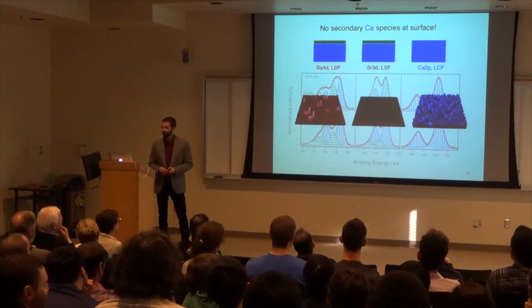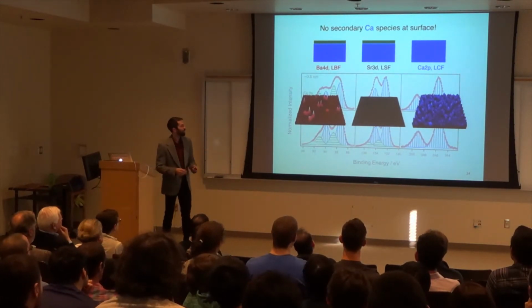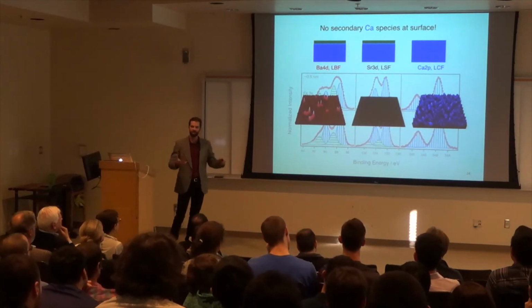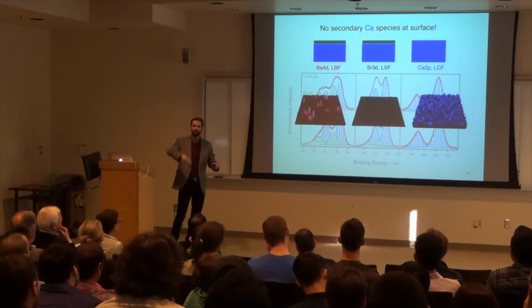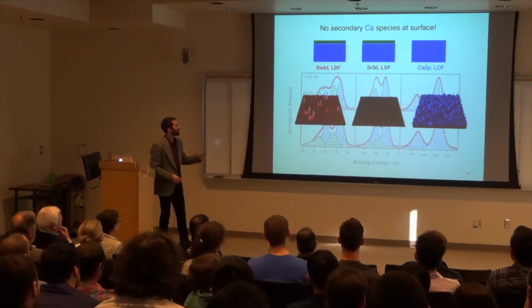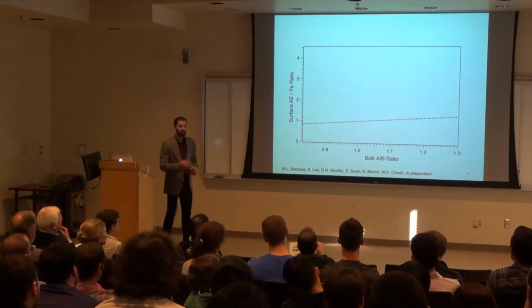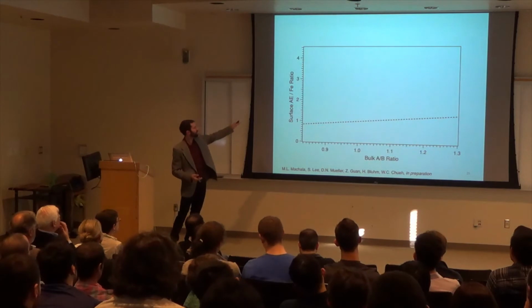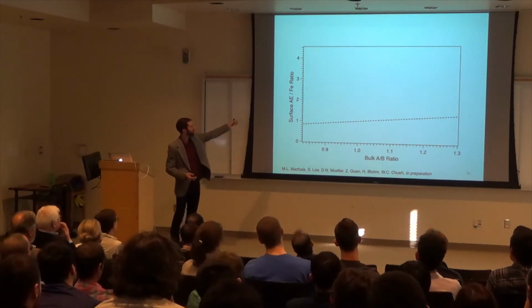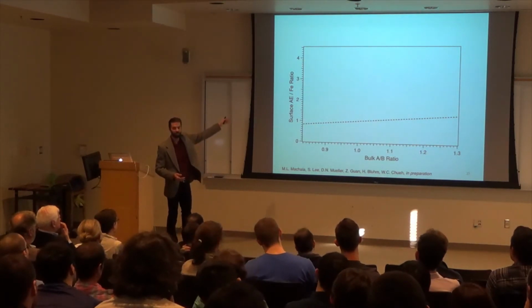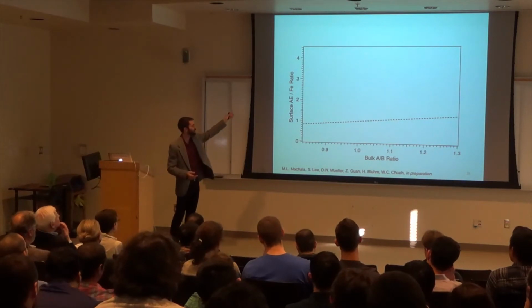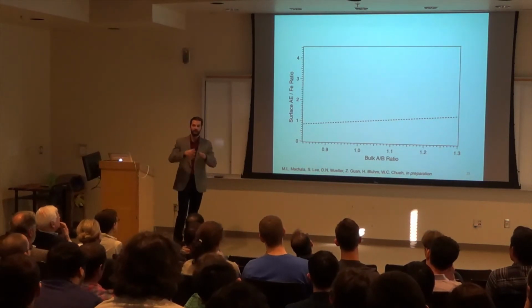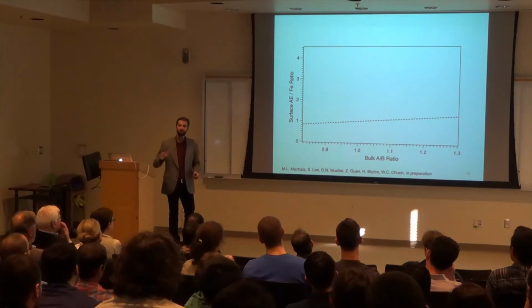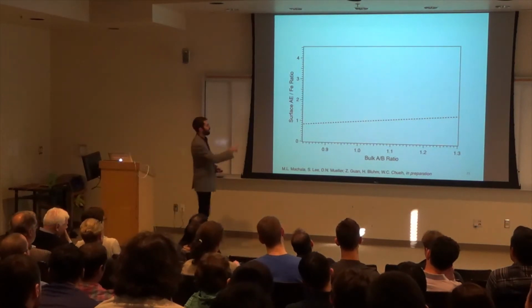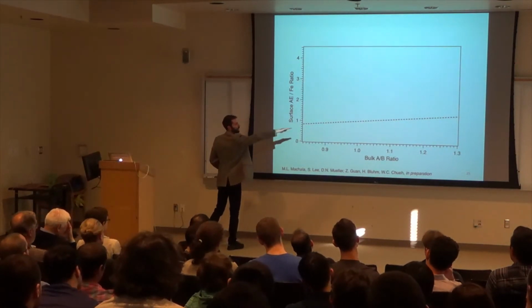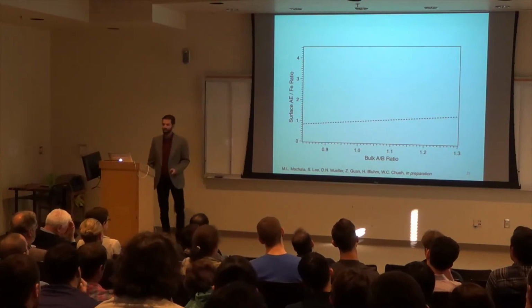And so right now, what we're going to do is try to make sense of these spectra. How can we make physical sense of these spectra? Because right now they're just a bunch of wiggly lines, right? So one technique that we used was comparing the ratios to each other. This is a graph of the surface alkaline earth ratio to iron ratio, so the A side and the B side, as a function of the bulk composition of the material. Now, if the surface looked exactly like the bulk, whatever we plot on here would be along this dashed line.